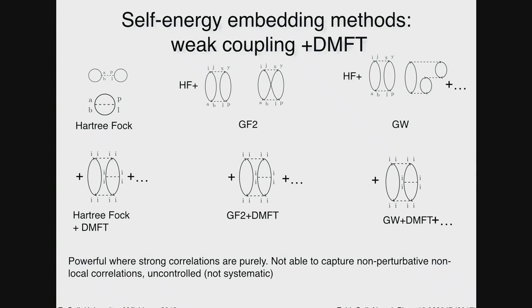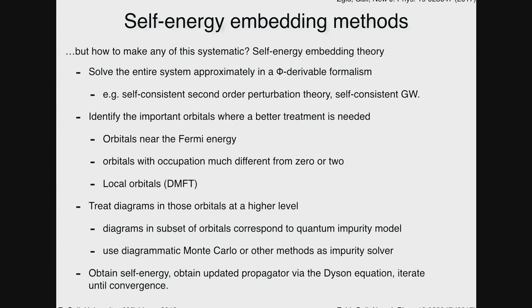Now, because dynamical mean field theory and those methods are written in the same diagrammatic language, it's actually straightforward to take them and supplement a Hartree-Fock, GF2 or a GW solution with a DMFT calculation: GF2 plus DMFT or GW plus DMFT. So this is now perturbative in the non-local correlations, non-perturbative in the local correlation, and it's not able to capture non-perturbative, non-local correlation in any way. It's still uncontrolled because there's no small parameter that will allow you to make this systematically more and more accurate.